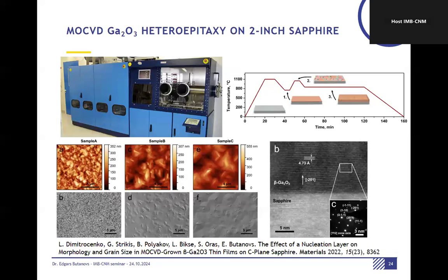So we developed a similar process for gallium oxide, which improved quite well the crystalline properties of the films. However, if you take a look at rocking curves, it's still not good, but it's close to the state of the art on heteroepitaxial films. So in future, it would be interesting, of course, to do homoepitaxy, because that's the only way to get really device grade films.